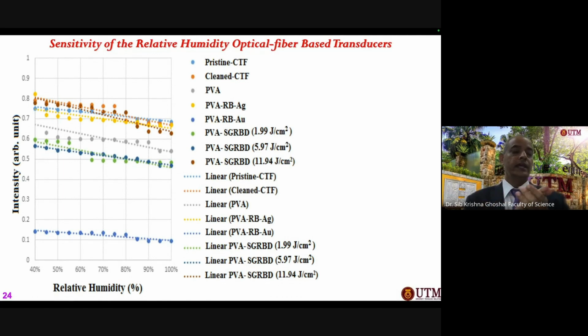So we started with variable humidity level and looked at the response of the transducers in the optical fiber geometry. As you can see here, the rose Bengal dye encapsulated silver nanoparticle, which is shown here by yellow, and then gold nanoparticle, which is shown here by blue, have very high sensing performance. And then when we make the optical fiber and coat it, and look at the silver gold rose Bengal dye at different fluence, the last three lines in this plot, you can see the sensing response improved remarkably, and therefore we can use these kinds of materials for high performance sensors for humidity detection in the future.